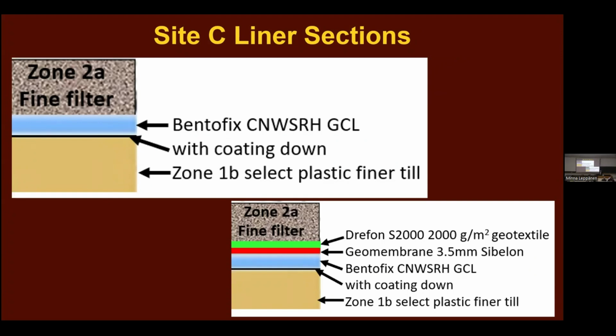I have to think about the fact that if I put a GCL directly on that till, moraine you would call it here, I think, which is at a moisture content of about 10, 12%, the GCL is going to suck up water from it. It's going to hydrate. Now, why do I care about that? Because it's going to suck up calcium and magnesium. It's going to experience cation exchange. And why do I care about cation exchange? Because this is in northern British Columbia, and it's going to be subjected to freeze-thaw and wet-dry cycles between the time I install it and the time it goes into practice.